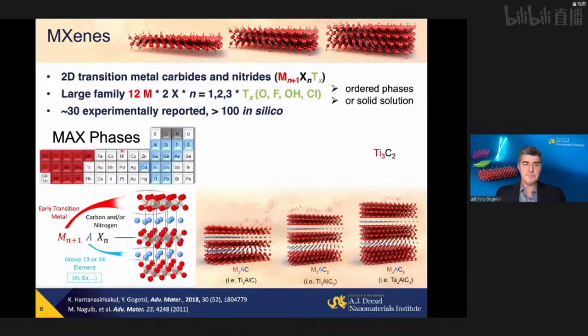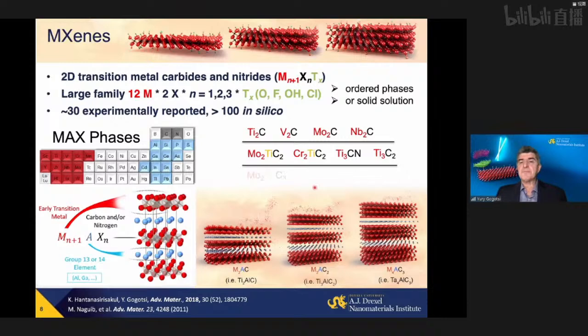A colleague of mine, Professor Michel Barsoum at Drexel, is really the father of that field. This is a large family of layered ceramics, which you can look at as transition metal carbide, nitride layers bonded by layers of this A element in blue in this periodic table. But these bonds are strong, they are not van der Waals bonds. So we have to etch the monatomic layer out of the ceramics to break apart the structure. And then we can produce titanium carbide Ti3C2, which was the first one, but also many other carbides and nitrides of materials.